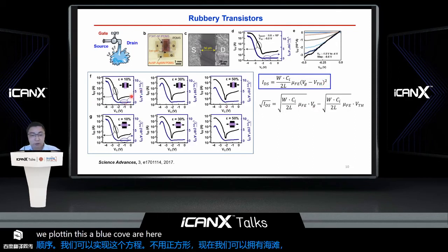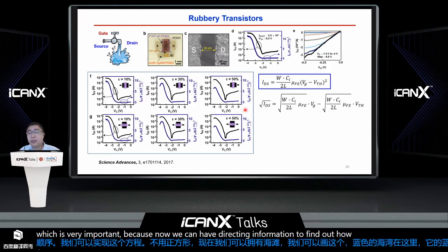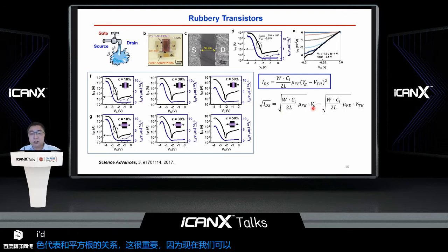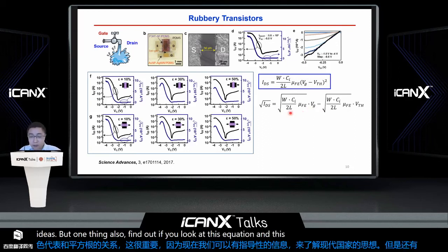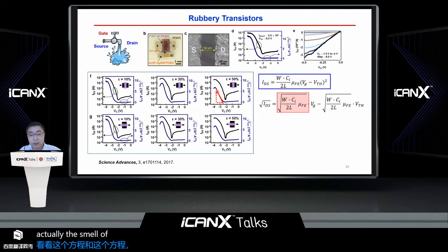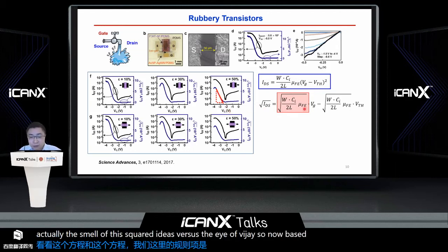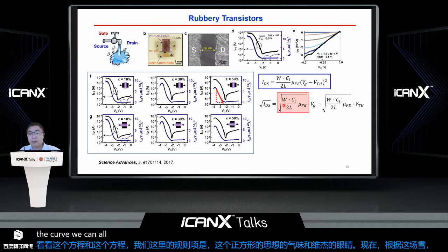This blue curve represents VG as a relationship to the square root of IDS, which is very important because now we have direct information to find out how the gate modulates the IDS. If you look at this equation, the square root term over here is actually the slope of this square root IDS versus VG. So based on this slope, we can calculate from the curve and derive the field effect mobility.